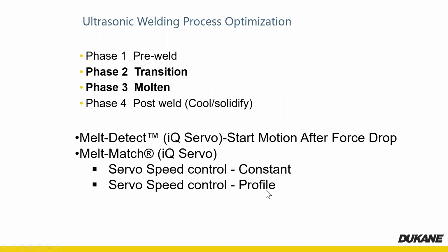We've got a 0.5 millisecond sampling rate on our generator, and that is important to this whole process. We need to be able to know exactly what's going on at a very high clarity level, so that we can adjust things and move things according to what the servo itself can do. So we've had this 0.5 millisecond sampling rate for a very long time, well before we had the servo welder as an option, knowing that we wanted to at some point control a servo, and that the only way to do that properly was with this kind of a sampling rate. So with that sampling rate, we can actually adjust this speed and this velocity in a profile. So in 15 thousandths of collapse distance, we can make up to 10 adjustments to that velocity as needed, and I'm going to go through in a couple slides why that would be and what the benefits of doing that are.